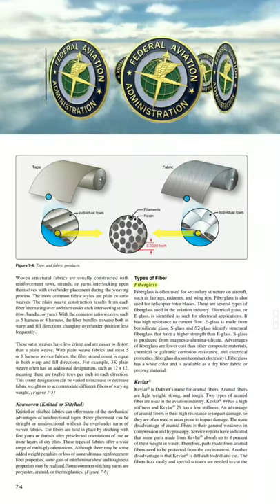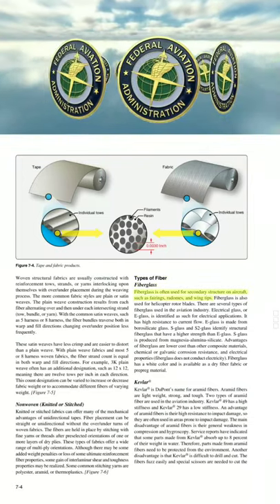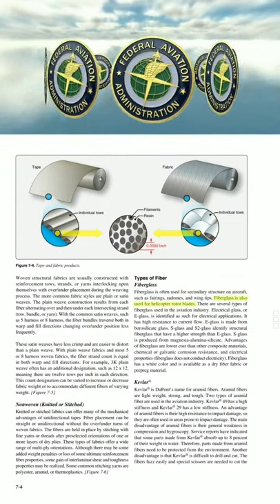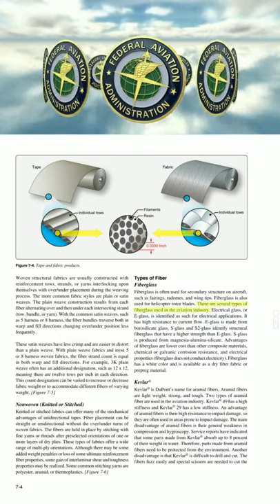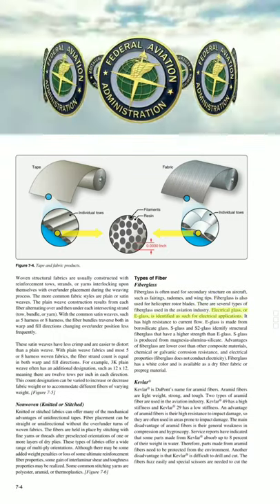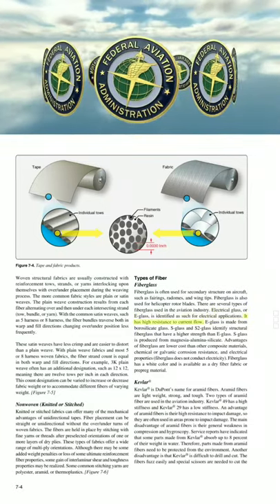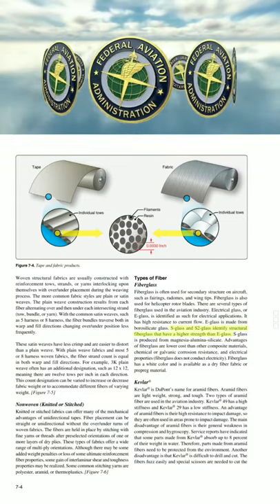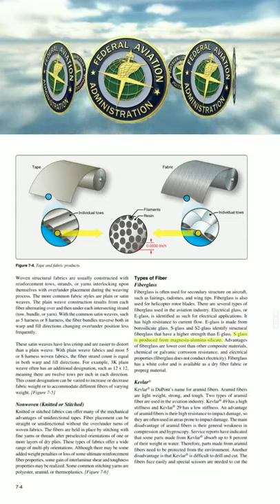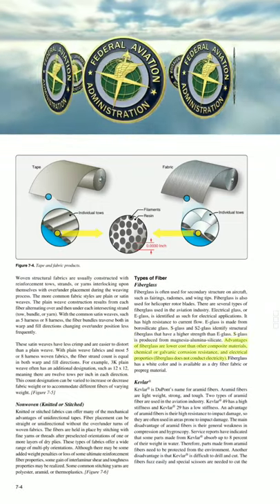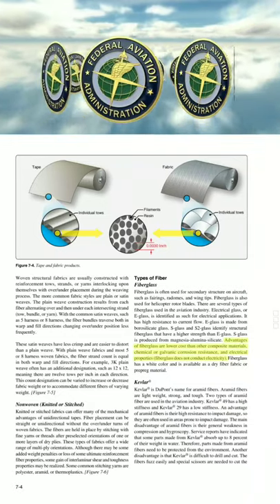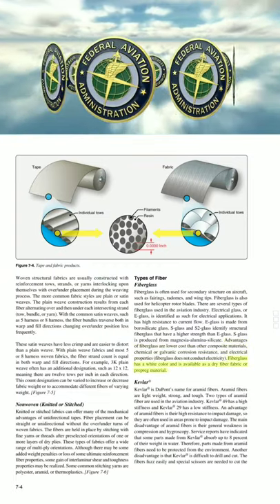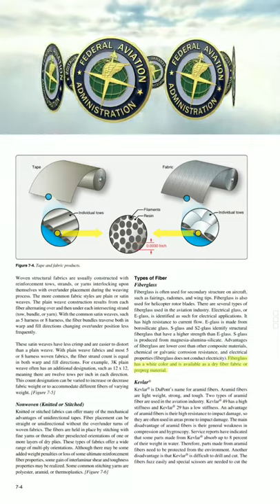Types of fiber — Fiberglass. Fiberglass is often used for secondary structure on aircraft, such as fairings, radomes, and wingtips, and also for helicopter rotor blades. There are several types: Electrical glass (E-glass) has high resistance to current flow and is made from borosilicate glass. S-glass and S-2-glass are structural fiberglass with higher strength than E-glass; S-glass is produced from magnesia alumina silicate. Advantages of fiberglass include lower cost, chemical and galvanic corrosion resistance, and electrical non-conductivity. Fiberglass has a white color and is available as dry fiber fabric or prepreg material.